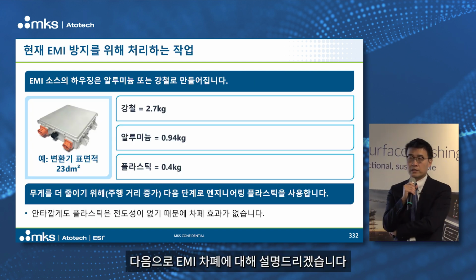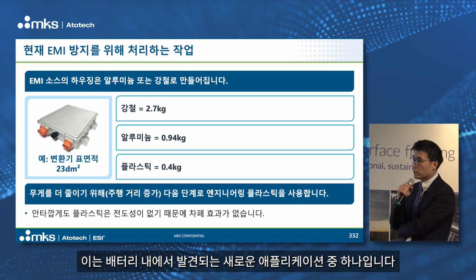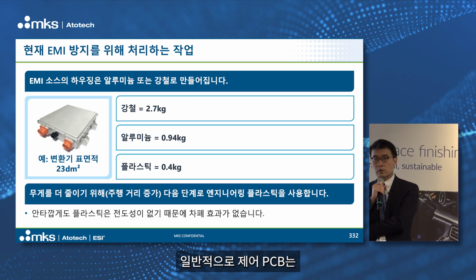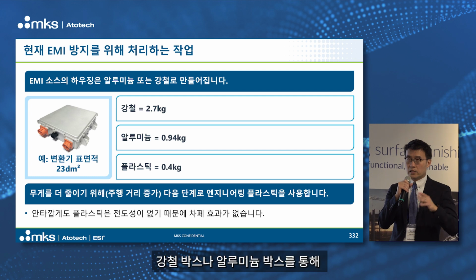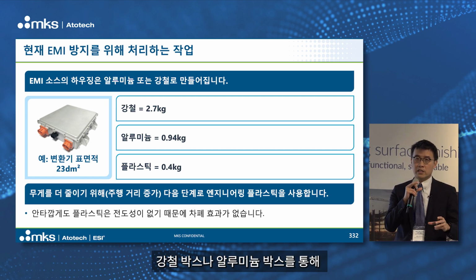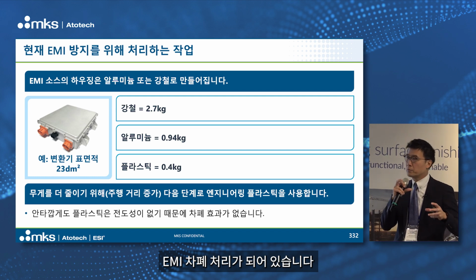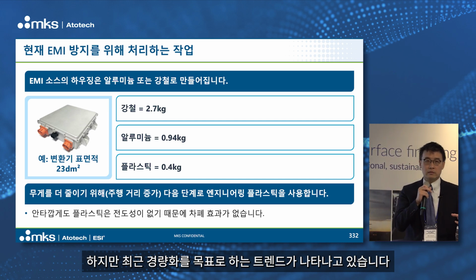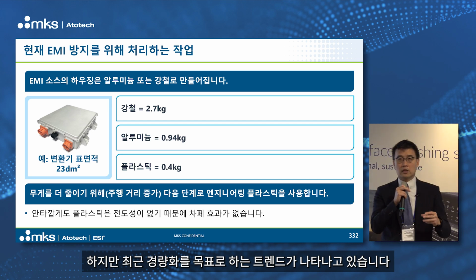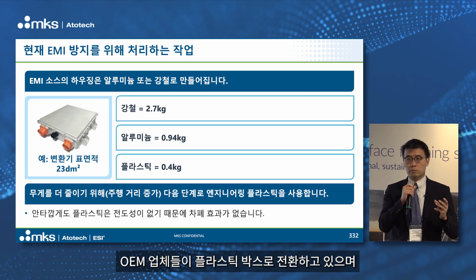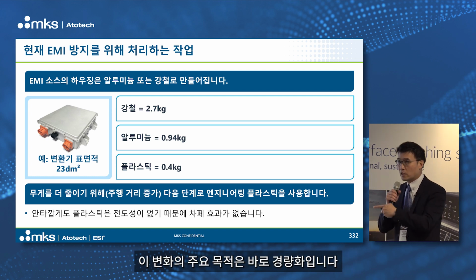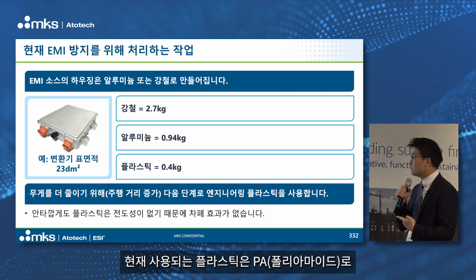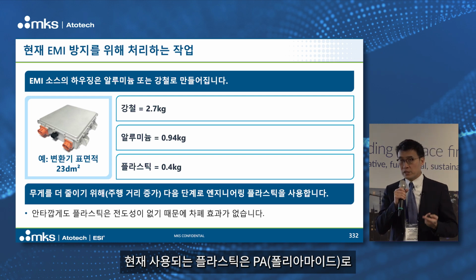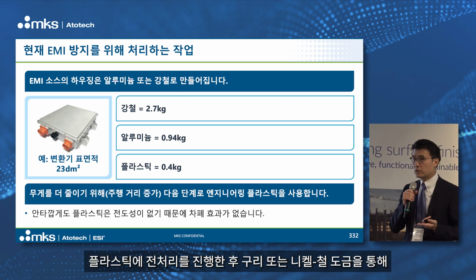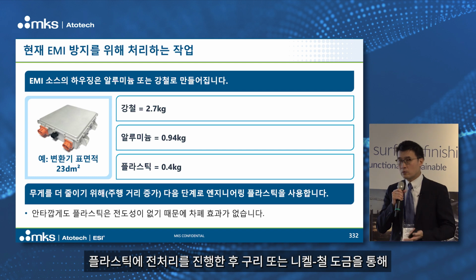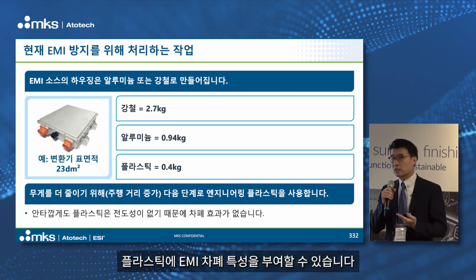Coming to EMI shielding. There's another new application that we see in the market, which is in the battery. There's normally a control PCB, and at the moment there's always a steel box or an aluminum box with EMI shielding that covers this PCB. And what we see now is a trend because of the lightweighting purpose. The OEMs are moving to plastic box. The motivation of this move is really lightweighting, and the plastic that we're using now is PA, which is an engineering plastic. And then we need to have pretreatment and also copper or nickel iron plating to provide the plastic with EMI shielding property.